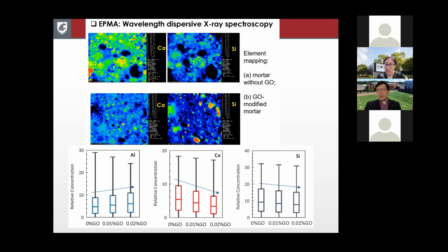My experience, 30 years ago as a PhD student, was that at the time montmorillonite nanoclay was sold by the gram, and now you look at it, it's used everywhere and sold by 25-pound bags, basically. So it's just a matter of improving the application scenarios so that you achieve economy of scale. Even if sold at $2 per gram, we did some rough calculations, it's still affordable in this application because we're only dealing with 0.2% by weight of cement. And you're achieving benefits in terms of strength and durability.